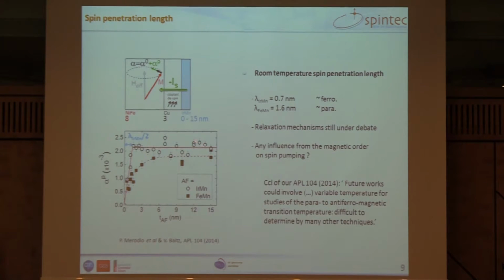From this data, we were also wondering if there is any influence from the magnetic order, because we know that we are certainly not antiferromagnetic all the way through these thicknesses. I mean, the thinnest layers are probably paramagnetic. At this stage, we also had the intuition that by varying the temperature, we could work out the Néel temperature. But we had this intuition simply because we thought that you would change the absorption mechanism by changing from an antiferromagnet to a paramagnet. So we will see further in the talk that it's possible to work out the Néel temperature, but the mechanism is different. So in the next slides, I am going to discuss this.